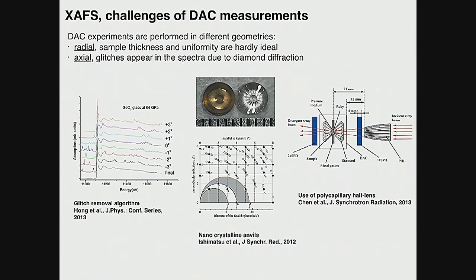So you have, remember the diamond anvil cell, how it is shaped. You have 2 opposing diamonds. You can actually go through the gasket material, so you need to have that gasket made of a material that will allow enough photons to go through, so it's usually beryllium. But if you go through that way, it's very difficult to have the right thickness throughout the entire size of the beam. In the axial geometry, luckily diamond is basically completely transparent above 10 keV, so you have so many elements that you can probe the edge of.